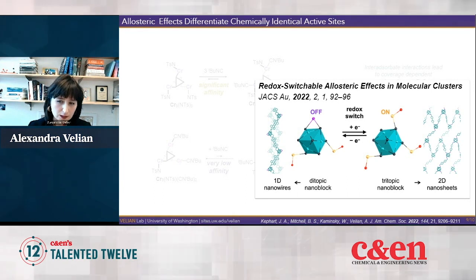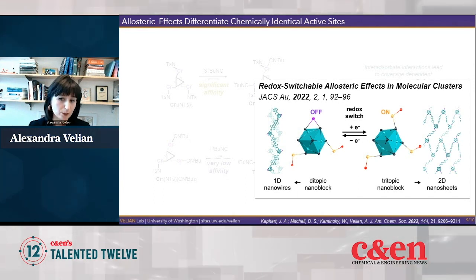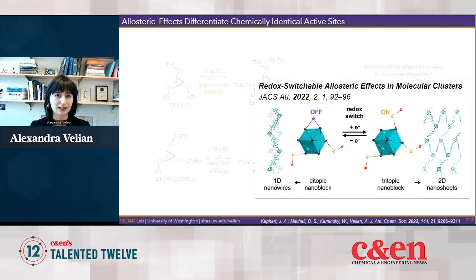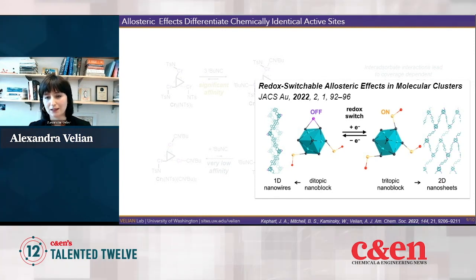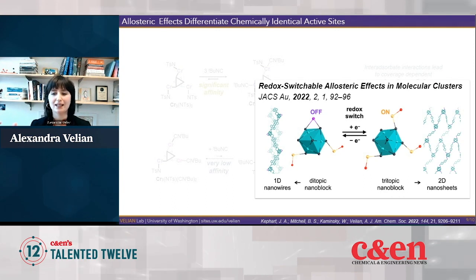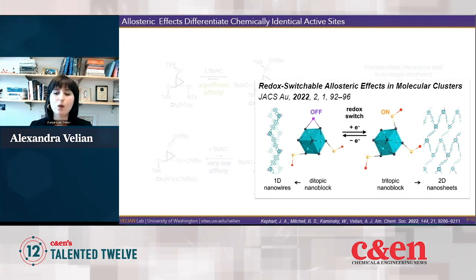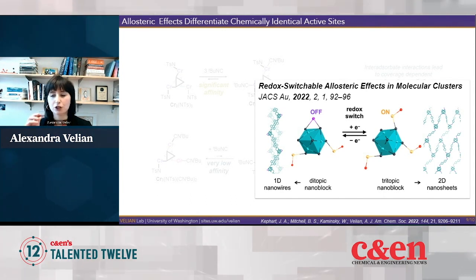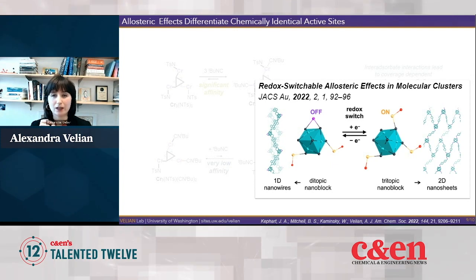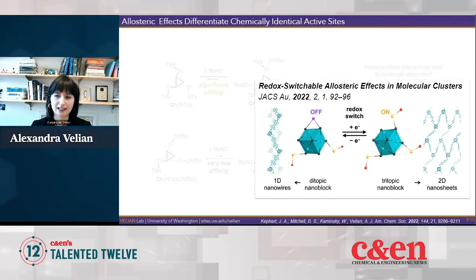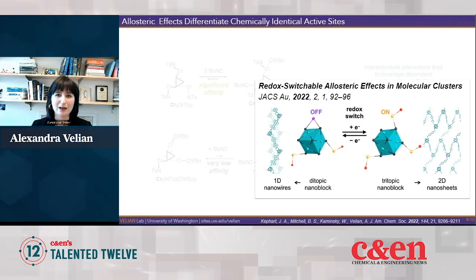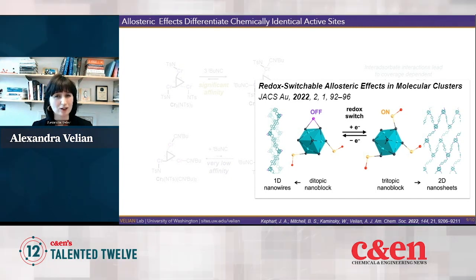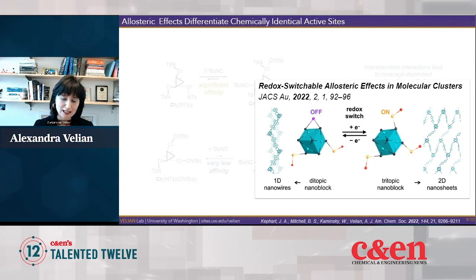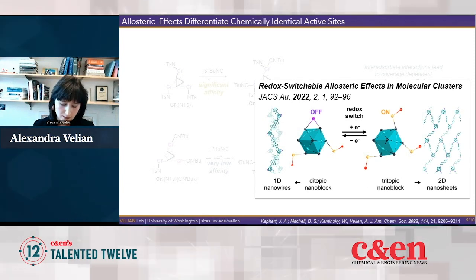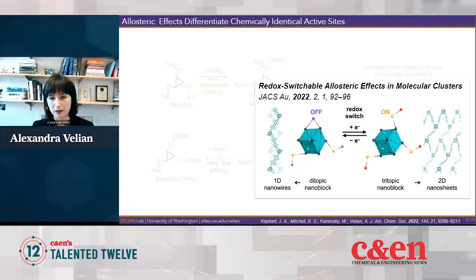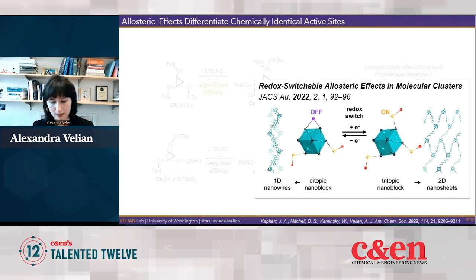And so because only two of these edge sites engage with ligands, we harness that to prepare dimensionally controlled or pre-programmed materials like wires. And on the left is a skeleton of a structure of such a wire. The cool thing is that by taking advantage of the chemical non-innocence of the support and oxidizing it, we actually can turn on selectively the coordination of a single site on the cluster surface, turning this into a tritopic building block that can enable the synthesis of two-dimensional van der Waals nanosheets, and that's what's depicted on the right side of the slide. And so I think these kinds of stimuli responsive materials are something that we think about a lot, especially intertwining it with catalysis.